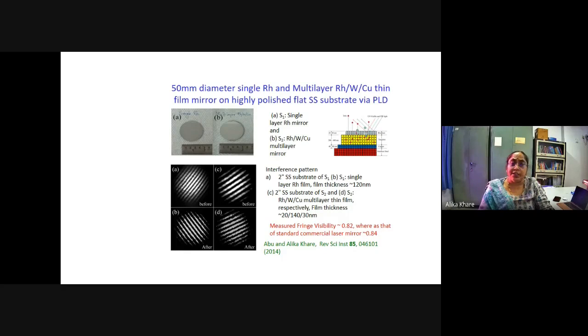And these were deposited onto stainless steel (SS), because in the tokamak only SS was allowed, glass was not allowed. So this was the substrate without deposition, and this is the one which was the deposited one.